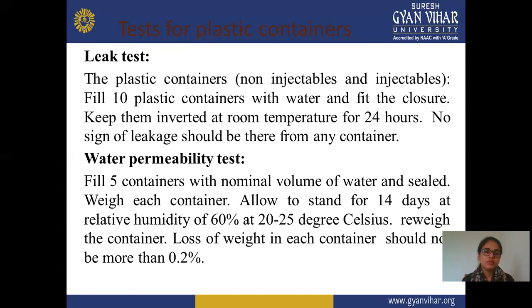In this test we take only 5 containers, seal them with water, and weigh each container. After weighing, you keep the containers for 14 days at a specific condition, relative humidity 60% and temperature 20 to 25 degrees Celsius. After this, you weigh the containers again and check how much weight is lost. It should be not more than 0.2%.